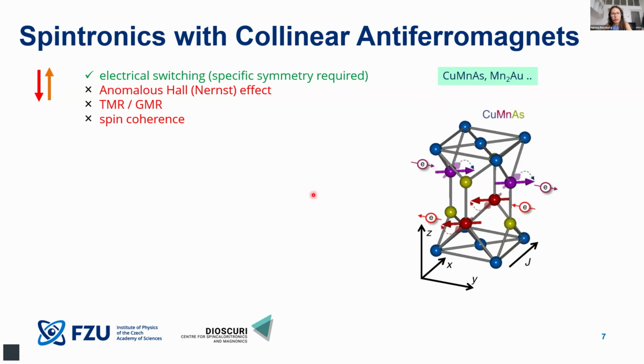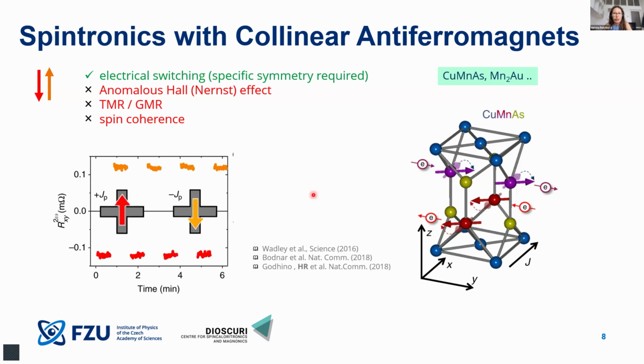And one more thing, which I think is just a side note: these effects are not showing only the switching which I am showing here, but they are also sensitive to second order effects, because these broken symmetries allow for them. So what we showed here is that even when one flips the Néel vector in this material fully by 180 degrees, which in principle should not give rise to a signal in the first harmonic, we can detect the switching in the second harmonic, in this sort of nonlinear effect.